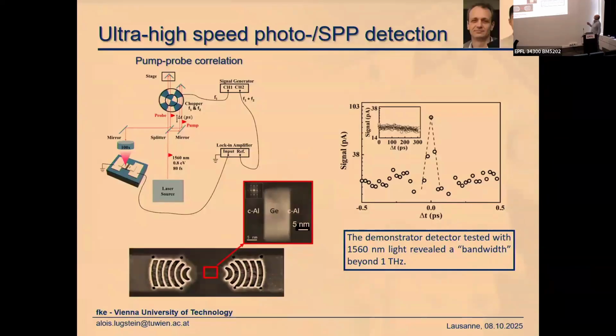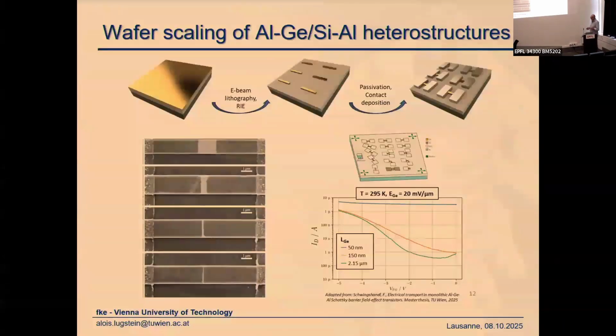Together with Juraj Damo from the Photonics Institute, we made these cross-correlation pump-probe measurements. And indeed, we saw that, I don't want to state that we have a super fast detector, but at least one of the mechanisms in the decay of the plasmon is super fast. So that will probably enable detectors with a bandwidth beyond 1 terahertz. Okay, so we probably have a super fast detector.